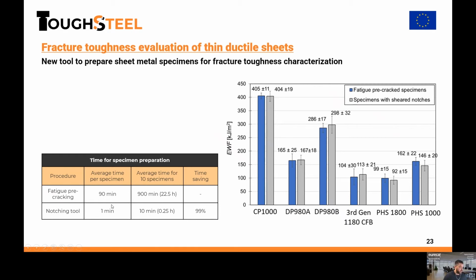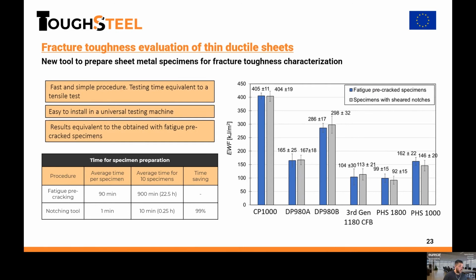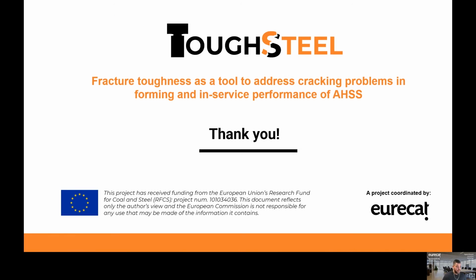We are talking about a reduction. We need around 90 minutes per specimen for fatigue pre-cracking, an average time of 3 working days for testing the material, but with this new procedure we can test it in only a few minutes. And the aim of this tool was to foster the implementation of these techniques at a more industrial level, making this fracture toughness testing procedure easier and more accessible to the industry. And that was my last slide. Thank you very much for your kind attention, and I hope there are questions.